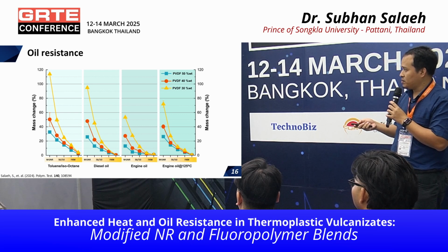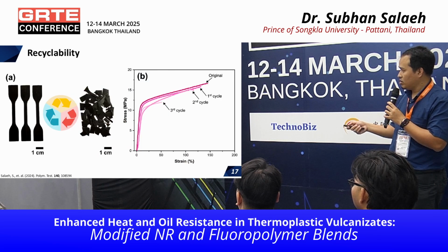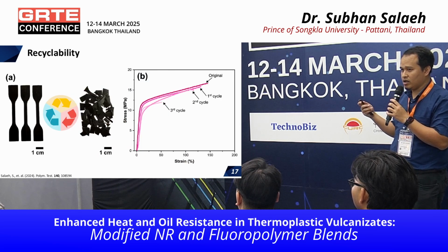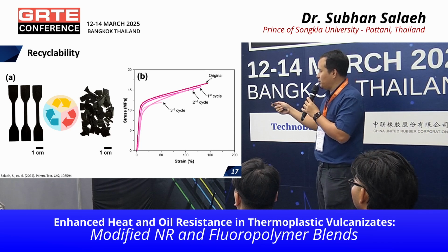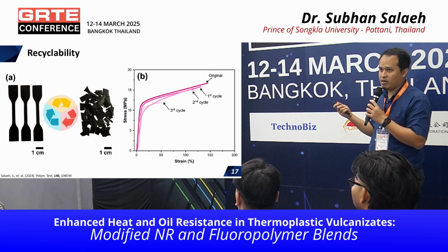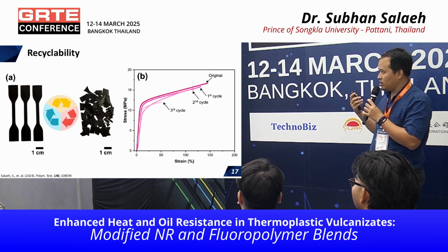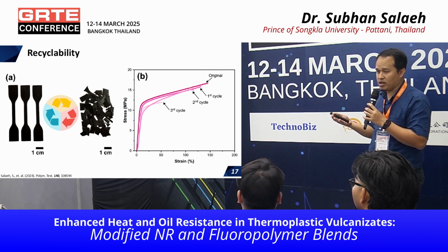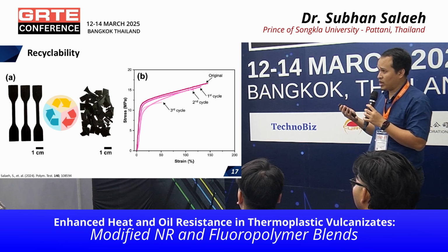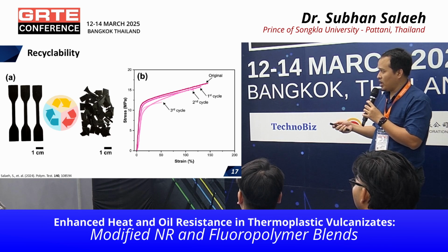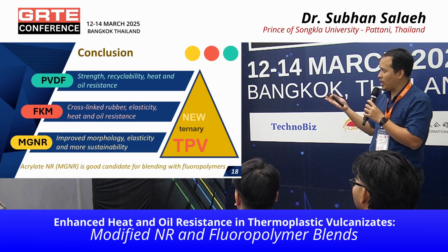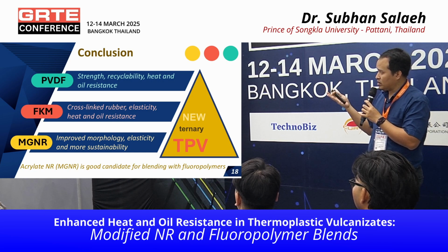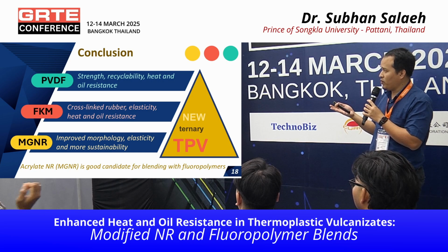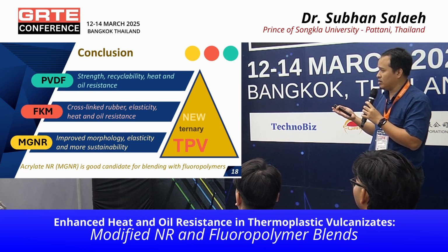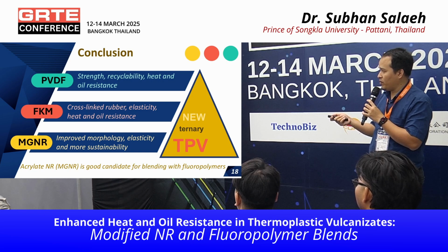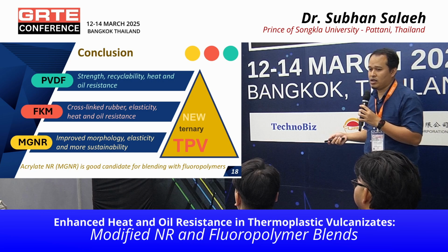And also this TPV can be recycled. So it is like a thermoplastic, but at the same time it exhibits good elasticity like rubber, with high elongation at break. So it means that we can prepare a new thermoplastic vulcanizate by using modified natural rubber and FKM. PVDF improves strength and recyclability, and FKM improves elasticity and oil and heat resistance. And with acrylate rubber, we can improve the morphology, elasticity, and sustainability of the TPV.